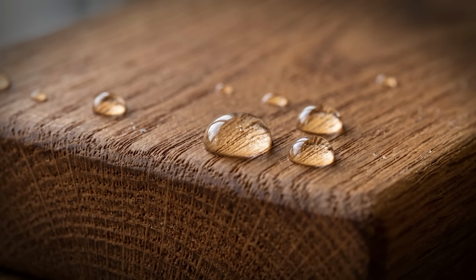But here is what separates it from every synthetic finish on the hardware store shelf. Modern polyurethane, modern varnish, modern epoxy, these materials cure on top of the wood. They form a plastic film over the surface. That film is rigid. Under UV exposure, under thermal cycling, under the mechanical stress of a flexing hull, it cracks. It peels. It fails at the interface between the coating and the wood. And once it fails, moisture gets underneath and the degradation accelerates.